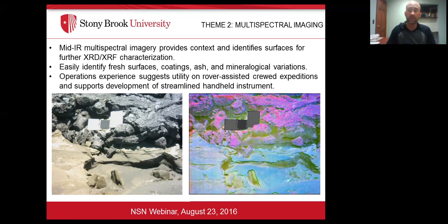When we make false color infrared images, though, using this camera, we see very big differences. We see these kind of greenish spots. We see these bright blue areas that happen to be volcanic ash. And we see these bright purple areas. It turns out these purple areas, even though they look like black lava rocks here, have a very, very thin coating of silica, or SiO2, on the surfaces as a result of the interaction of the acid vapor from the volcano with the rock surface. Without this infrared camera, we wouldn't be able to tell that. So this is a type of instrument that could be really useful for helping us to high grade the rocks and choose what types of rocks we'd want to take back if we brought one of these types of instruments to the moon.